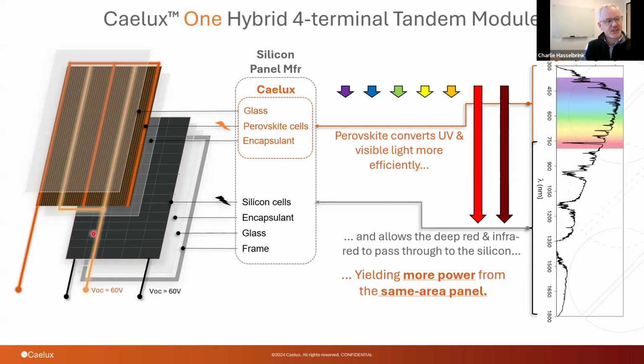Now we have 60 volts here, which is a typical number for silicon panels. Of course, it's never exactly 60. In fact, we just did a delivery of some panels at 57 volts, which was the requested voltage, so we had to adjust the thickness of these cells a little bit. We also play games with the matching of these strings. Ideally, you match them so that the tabs we put over the product line up with the spaces between the cells for minimum shading. But these tabs are only a few millimeters wide, so you don't lose too much current through them.